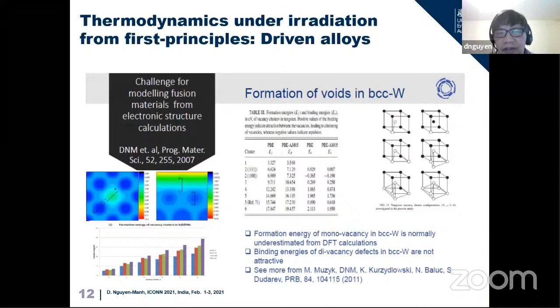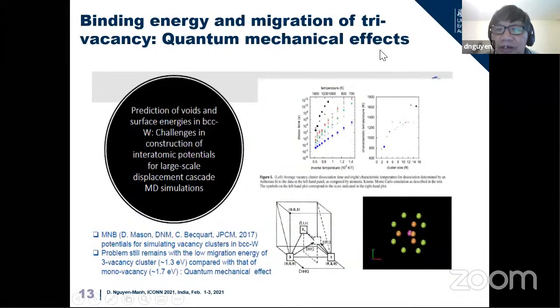So it is essentially a quantum mechanical effect; even from the point defect calculation, we see that the point defect has quantum mechanical effects. And when we go to migration of the vacancy cluster, we see that it is not easy to use a classical potential to predict it. For example, if we look at the tri-vacancy here, you can see that the saddle point configuration of the tri-vacancy goes to a minimum and cannot be predicted by the conventional interatomic potential. So essentially there are many quantum mechanical effects when you go into detail, and they affect the quality or accuracy of the understanding of, for example, voids in tungsten.